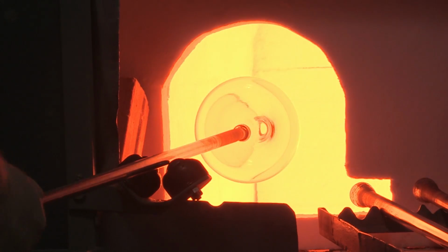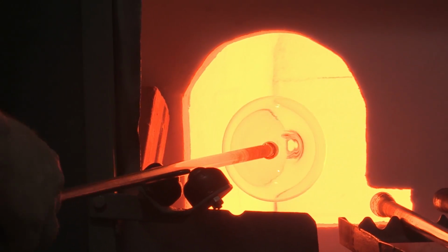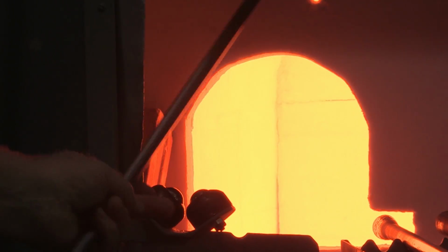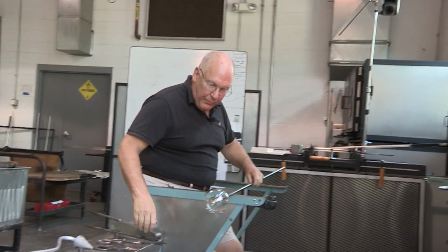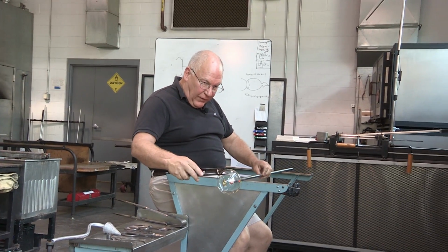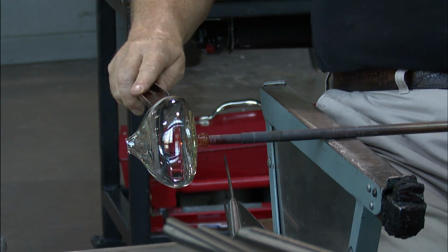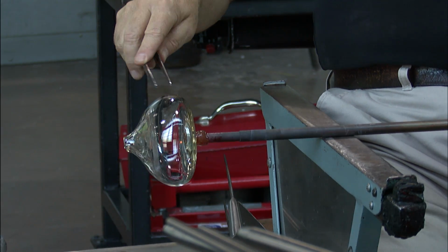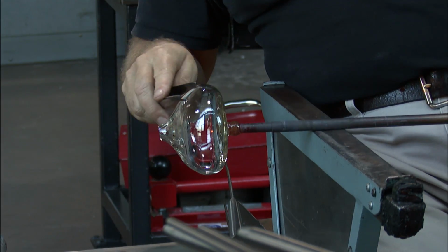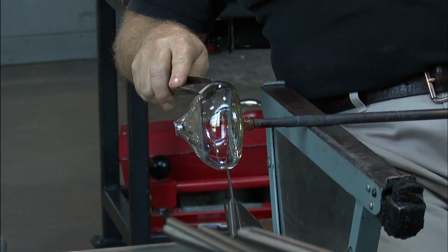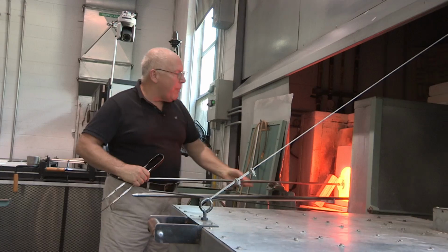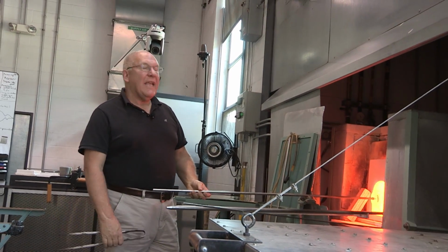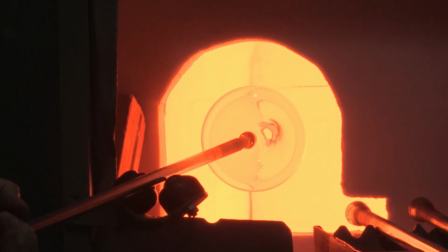It's a little bit off center. So now I've flashed it. If I touch it with the pincers to push it onto center, it could possibly crack it. So I push downward, and I'm looking at the profile to make it centered. There we go. It's pretty good. I reheat and open to about 1.5 inches or so.